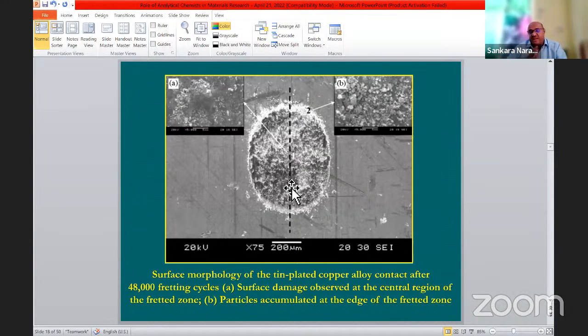So how is the scanning electron microscope useful to understand the mechanism of fretting corrosion of tin-plated copper? This area is very small. You can see the entire area. This is a 200 micrometer scale, so it is about 400 to 500 micrometers only. Normally we started with 180 microns. This is the movement, and it generates slowly. It comes in an elliptical.